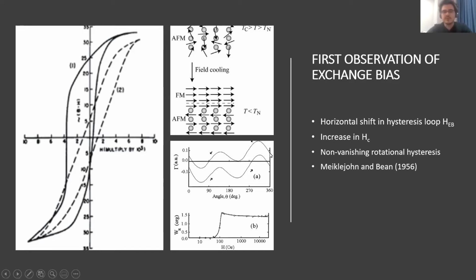They start to rotate the ferromagnetic layer, but while they're coming back, they see that they don't go over the same line. They also see unidirectional anisotropy here, because uniaxial anisotropy has two minima, which are pi degrees apart. But as you can see, we have one minimum here, which denotes a unidirectional anisotropy in our material, which comes from the cosine phi component in the energy term. Uniaxial anisotropy, by contrast, is denoted by the sine squared phi component.